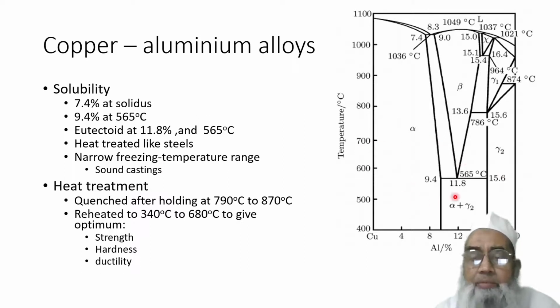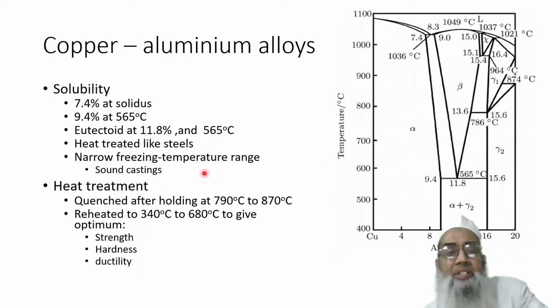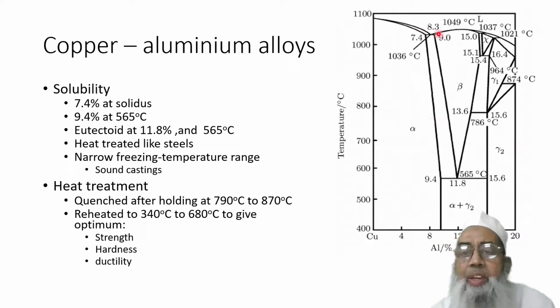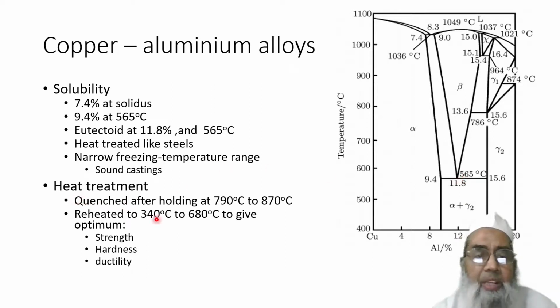Now if we can control the freezing temperature range, then we can have a sound casting. It is very narrow, and therefore can be controlled by different mechanisms. And also the eutectoid at 11.8% at 565 degrees centigrade gives the heat treatment facility. This heat treatment can be done by holding the component at 790 degrees centigrade to 870 degrees centigrade, and then cooling it. Then we again reheat it so that we can optimize strength, hardness, and ductility.